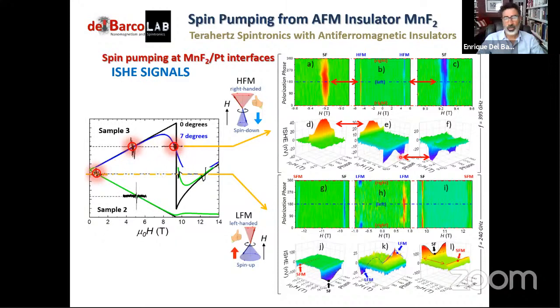If we go deeper into the spin flop transition, things are a little different. I mean, the symmetry is the same. So we have a minimum when we have a minimum in the high frequency mode, but now the signal has totally reversed. And this is a surprise, we didn't expect this. We cannot even explain it with the theory that we have used. And then, of course, we can keep going into the quasi-ferromagnetic mode, and then we see a totally different behavior. Basically, there's no modulation, and the signal is, again, positive instead of negative.